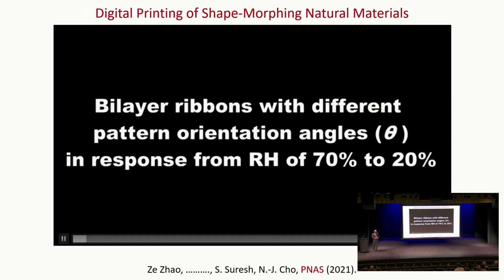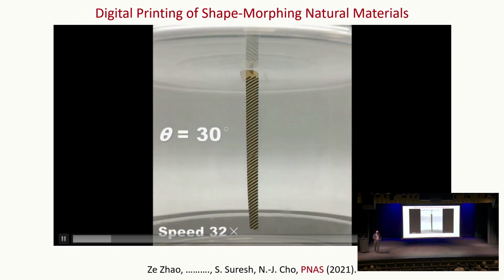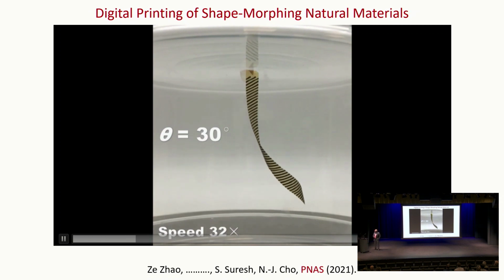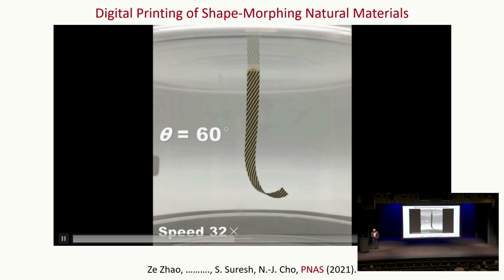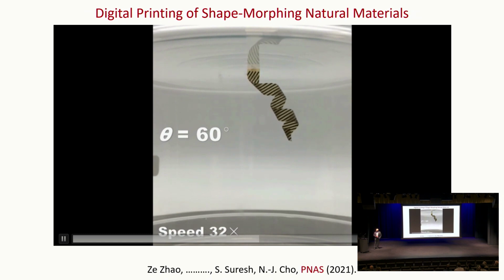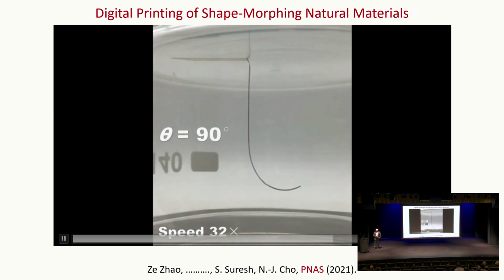So here is the actual experiment, speeded up. At 30 degrees, you can see the shape change. At 60 degrees, you have a different shape change. At 90 degrees, it starts to coil. So all we did, the only change, is the orientation angle of the lines on the pollen paper.